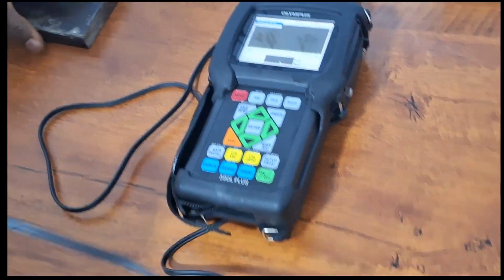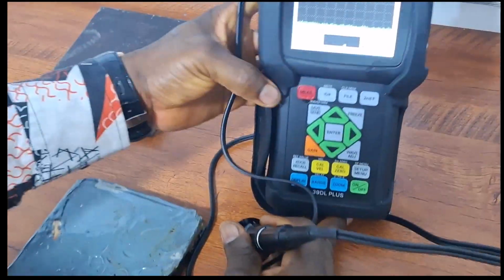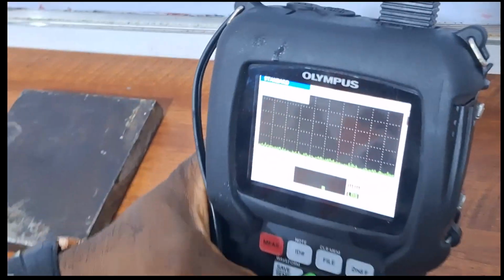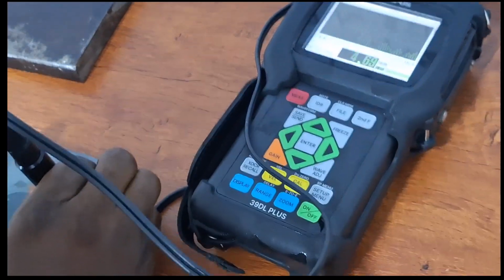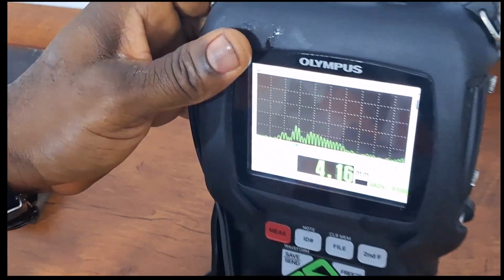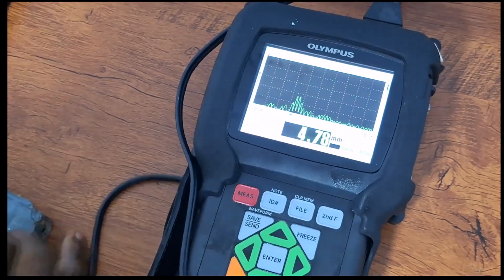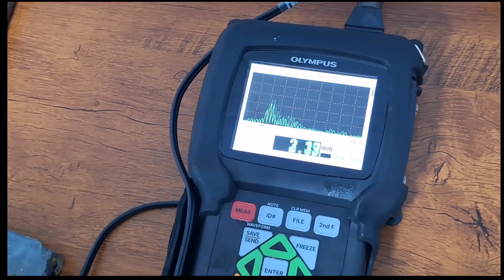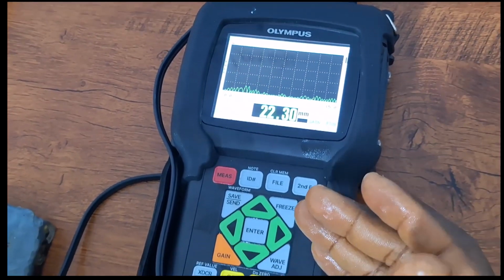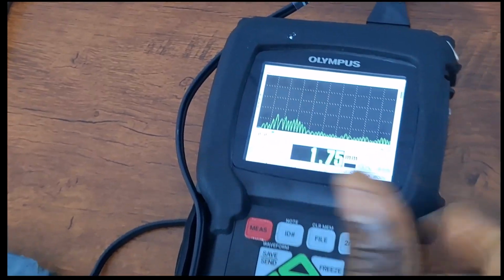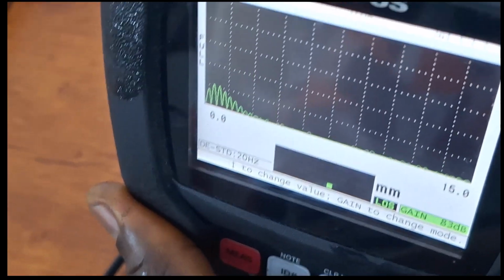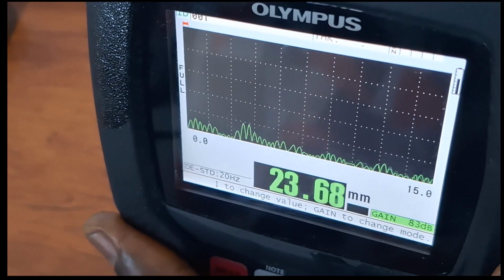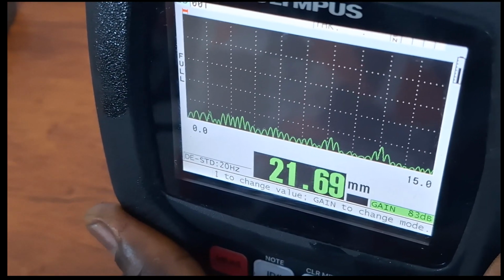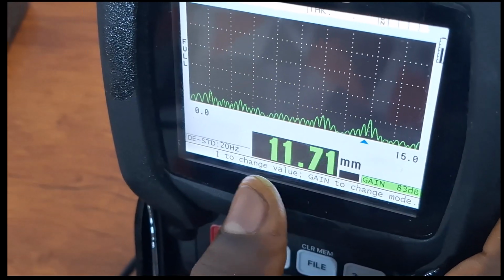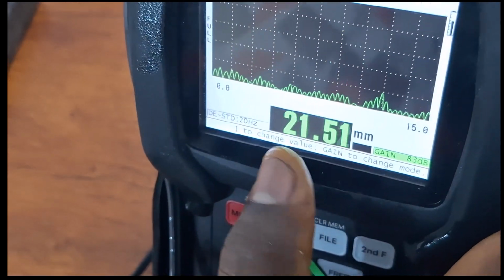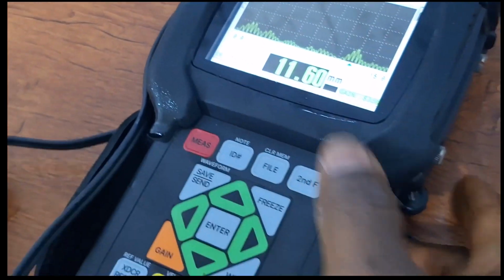If we check our 39DL Plus, now I'm on that mode to set. If I pick standard, which means in this case, it does not consider the coating. If you look at the reading, at some point we are trying to get the reading of the coating, which is about 2 mm. In this case, it's giving me the reading of just the coating. When I go to an area where the coating is good, I'm getting 22 mm as my reading. 21, 22. You see, in this case, this plate is 20 mm, but I'm getting my reading of both the coating and the plate.